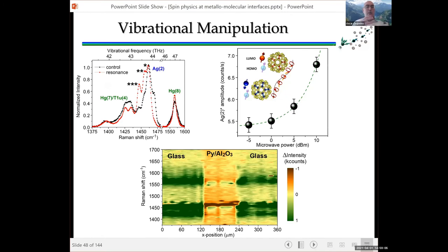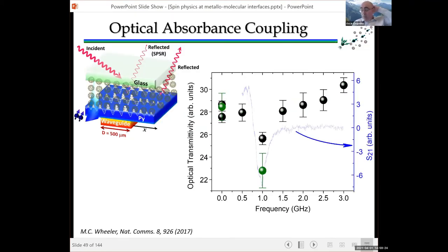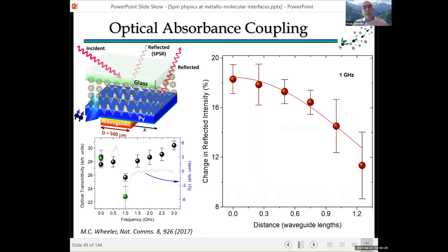And what you see is that during the resonance, when you are spin pumping, the Raman peaks of your molecules are shifted. So you have a different vibrational spectrum when you have the spin current in your molecules. And also you can see that the optical reflectance or absorbance also changes. So you enhance the optical absorbance when you are in resonance, and the luminescence of your molecules also changes. So here you have a comparison of in resonance and out of resonance.